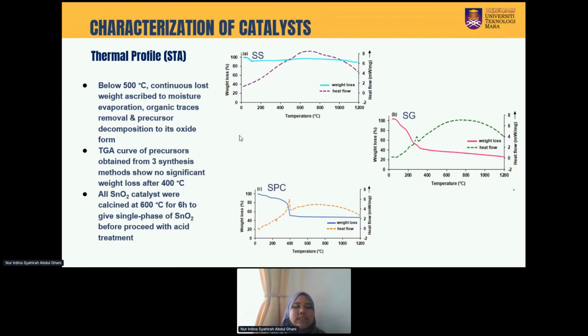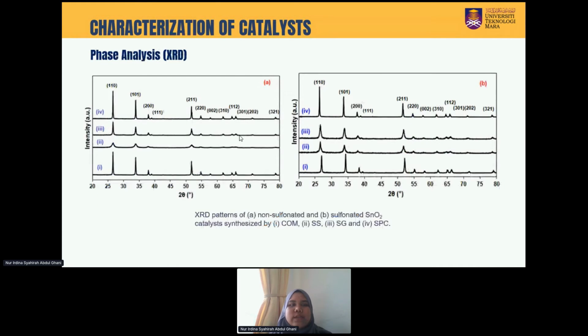The three synthesis methods show no significant weight loss after 400 degrees Celsius, and thus all the catalysts were calcined at 600 degrees Celsius for 6 hours to give the pure single phase of tin oxide before proceeding with acid treatment. So this one is the XRD phase analysis.